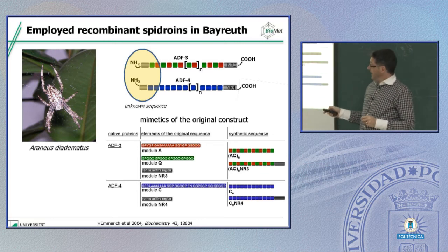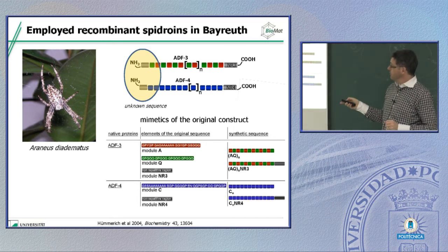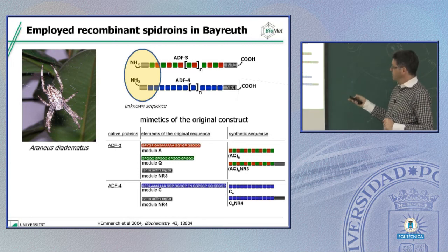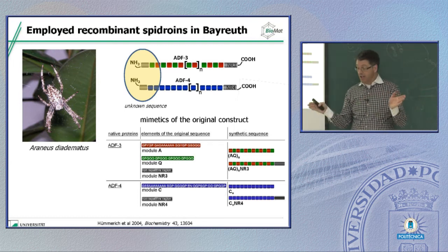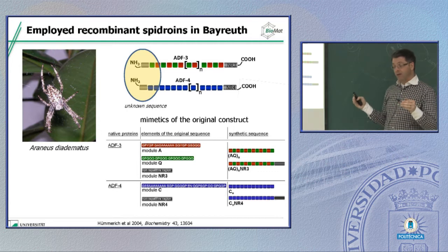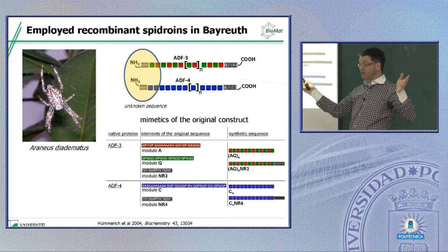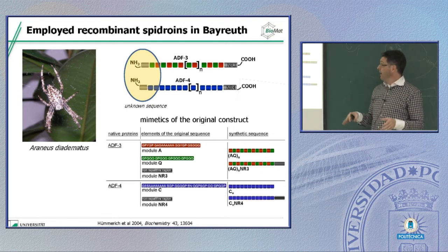What we did in the beginning was to make this back translation, making sequence modules and DNA cassettes, and then we can actually make synthetic sequences either with or without the carboxy termini, and we can vary n in a large regime. We're somewhat limited by bacteria because bacteria cannot produce really large proteins. Like 300 kilodalton is very hard for bacteria to make, so typically we work with proteins with molecular weights between 50 and 150 kilodalton.